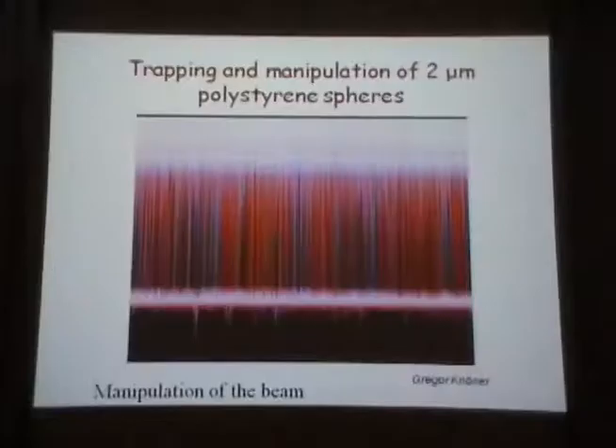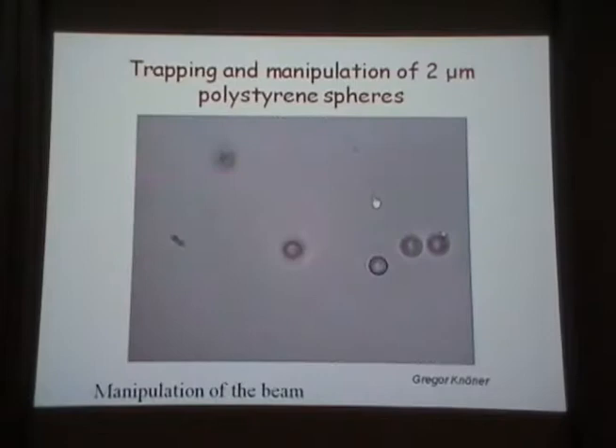Okay. So Hisham already showed you this. So here is a particle which is trapped. This is a 2 micrometer polystyrene sphere. It's trapped in a highly focused laser beam, 1064 beam. And we are moving the beam around, and we can see that the particle stays trapped. We can see that the other particles which are not trapped, we can see their Brownian motion. And we also can see that when the trapped particle is standing still, it also wiggles a tiny, tiny little bit. And that was the Brownian motion that Hisham was measuring.